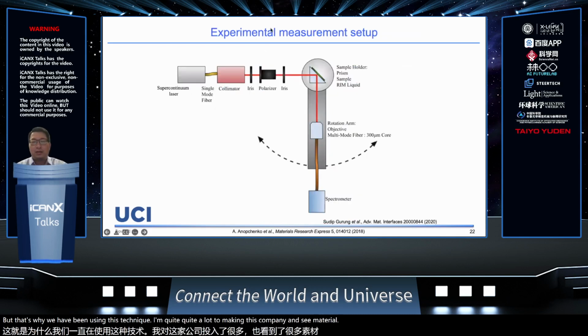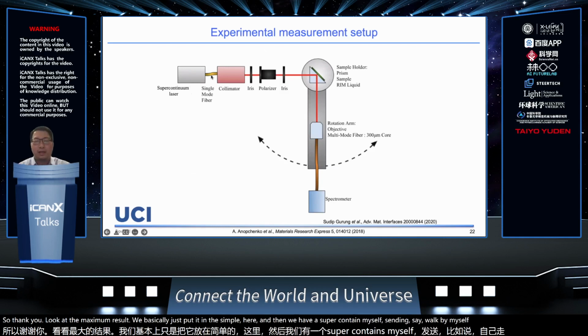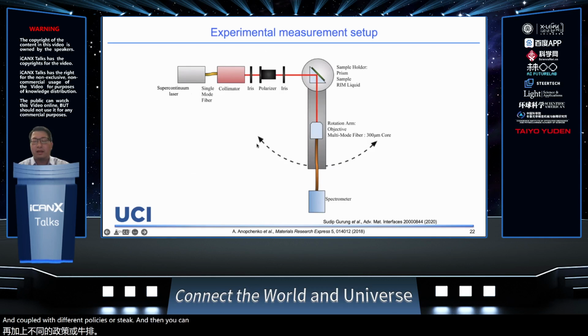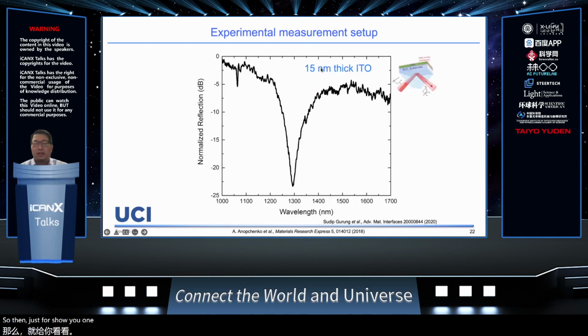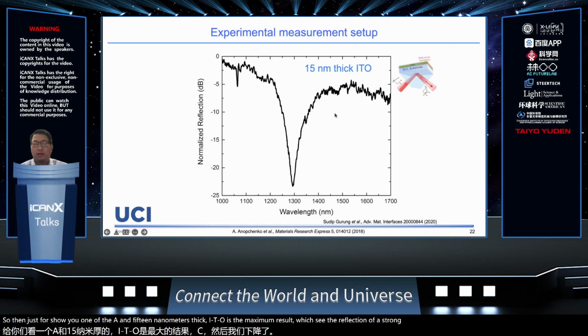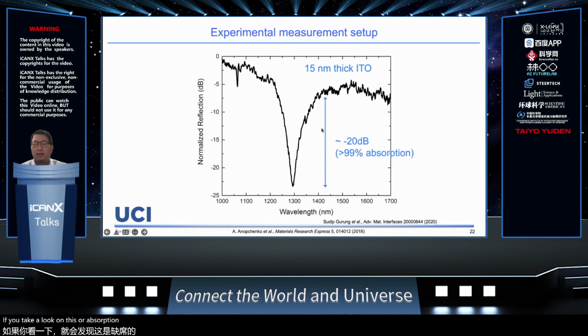Then to look at the measurement results, we basically put the sample in here, and we have a supercontinuum light source, which is a broadband light source, coupled to different polarization states. Then you can excite at different angles and collect at different angles with a spectrometer. Just to show you, this is the measurement result for a 15 nanometer thick ITO. You see in the reflectance a strong reflection dip, which corresponds to the ENZ mode excitation. If you take a look at this absorption band, it's around 20 dB, which corresponds to around 99% absorption. It's quite impressive. With only a 15 nanometer layer, you can absorb almost 100% of light.